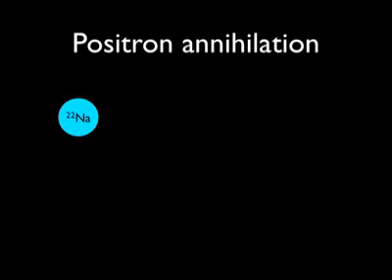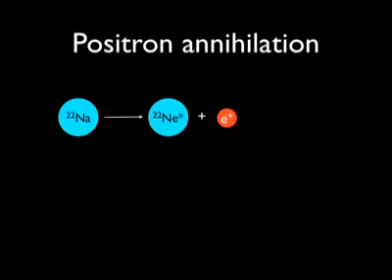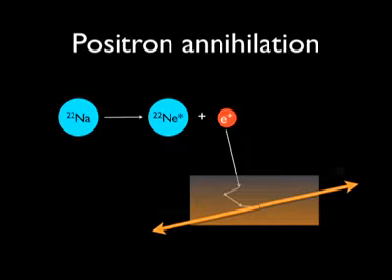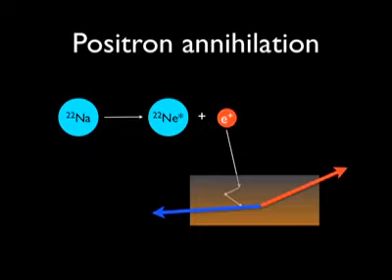Positron annihilation is a bulk probe of the Fermi surface. Positrons are emitted from a sodium 22 source and enter the sample being studied. They thermalize and then annihilate with an electron producing principally two gamma rays which are almost back to back. The small angle between them is proportional to the momentum of the electron-positron pair and as such contains information about the occupied momentum states and hence about the Fermi surface.